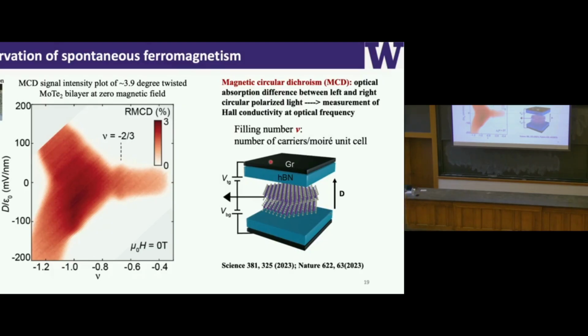In the measurement, what we use is called magnetic circular dichroism. We measure the optical absorption difference between left and right circularly polarized light. You can think of it as a measurement of Hall conductivity at optical frequencies. We also define a filling number nu here. The filling number nu means the number of carriers per moiré unit cell. So a filling number of, for example, -1 means there's one hole per moiré unit cell. If it's a fractional number, it means there's a fractional number of holes per moiré unit cell.